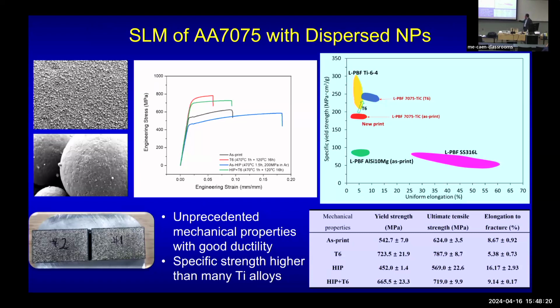We can go to 600 megapascal, about 8% ductility. Go to T6, we can go to almost 800 megapascal. It's much better than a lot of titanium alloys, I mean, on the specific strength side. And also with HIP, because it gets rid of cyclic porosity, we can get 16% ductility. If HIP plus T6, we can get about 9% ductility with 700 megapascal.